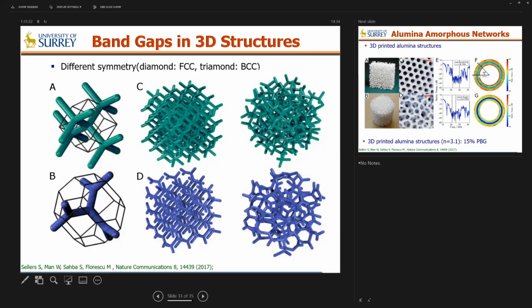And in the meantime, we can create disordered versions of this triamond network, just as people have created these amorphous networks to model silicon. The point that we take forward is that the band gap size, for which we calculated both diamond and triamond and obtained very similar values, seems to be related to the geometrical properties of the structure rather than the FCC-BCC symmetry.